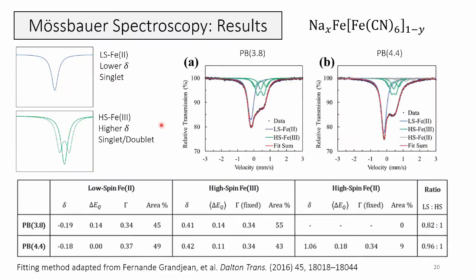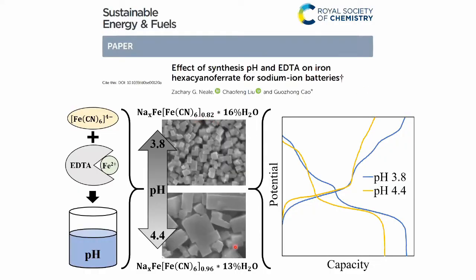All right. So the Mossbauer results, you have these data points, which is the absorption peak of my sample compared to the source. And you fit these different peaks that represent each chemical species of iron in the sample. So in this case, I have two chemical species of iron, and the area under this curve correlates with the concentration of that species of iron in my sample. So what I did is I took the area of each of these curves and I compared the ratio, and that would tell me the ratio of this iron coordinated to carbon, which is low spin iron, compared to this iron, which is high spin iron. So between my two samples that were made at different pH, I can look at the ratio between those two irons, and that would tell me the number of vacancies in my material. And then from that, I was able to derive a chemical equation for that material.